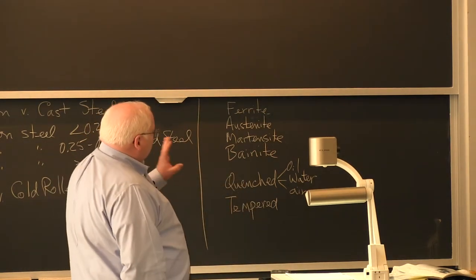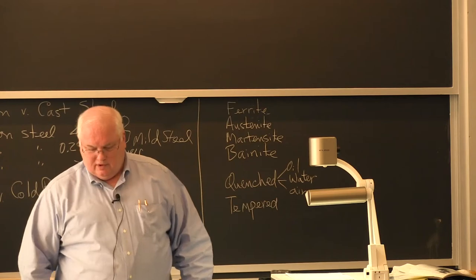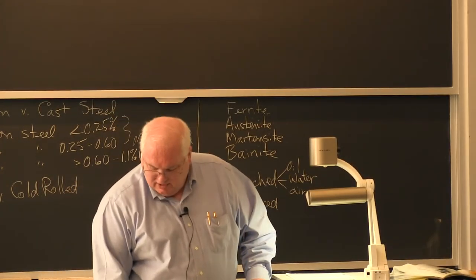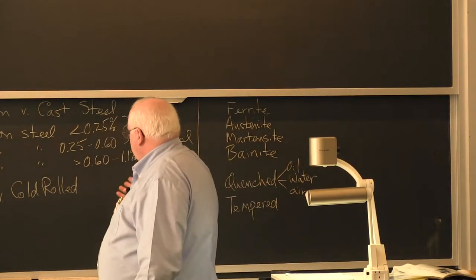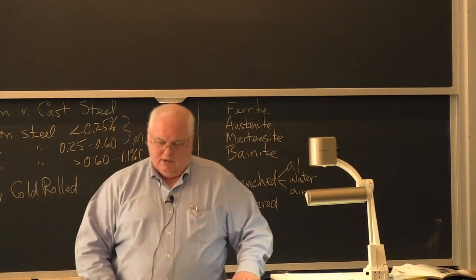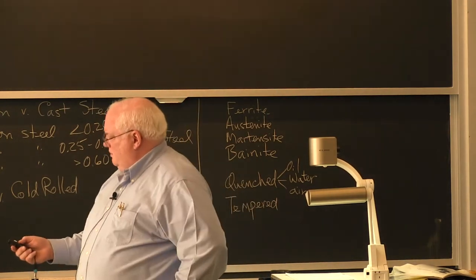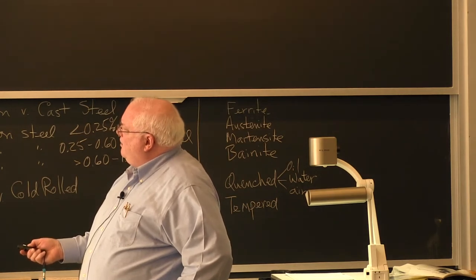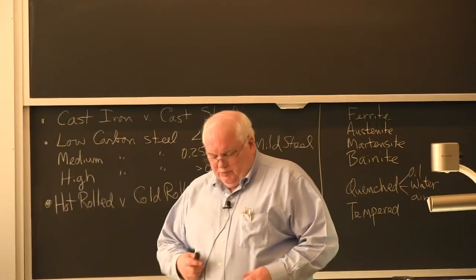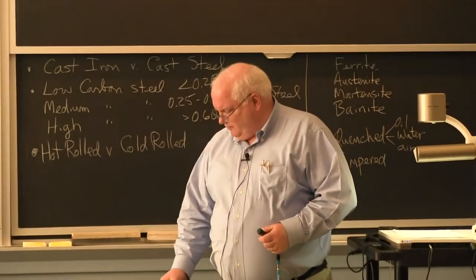Okay. So this quenched and tempered, what else do we have in here? We have annealed, which I can take any of these steels and heat them up to just above this little line right here into the austenitic region and hold them there and then cool them down slowly. Don't quench them in oil or water, and I will end up with an annealed microstructure and it will be nice and soft. About 30 to 35 KSI yield. Depending on the carbon content, it can be 60 to 90 KSI tensile, so far as that goes.